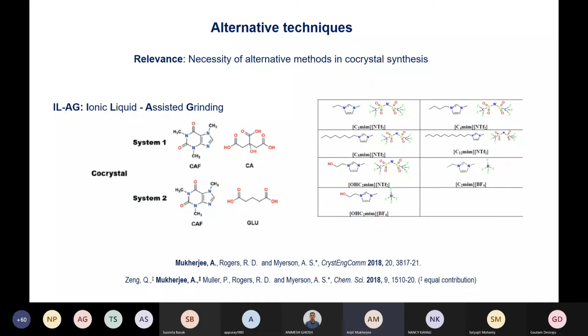There is always a necessity for alternative techniques in this space, because if you look at the patents published in the last few years on these co-crystals, you will see that most of them have been synthesized through slurry or liquid or neat assisted grinding techniques using organic solvents. And the problem there is we have only a few organic solvents which can be used for this purpose, because they are acceptable in the industry.